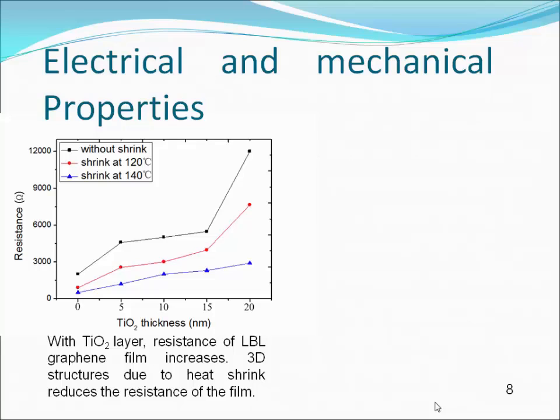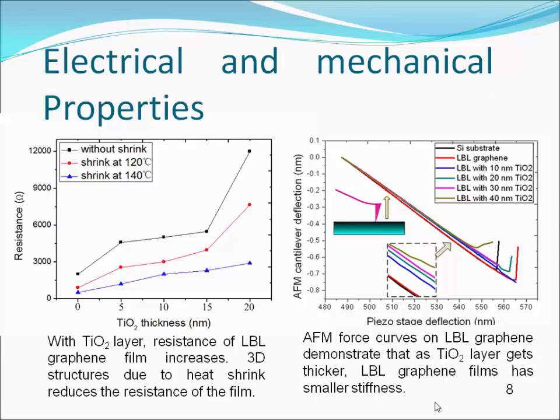On the other hand, the 3D structure after heat shrink can introduce small connections between the graphene nanoplatelets. So as a result, it can increase the conductance. Therefore, the resistance of these graphene components can be changed and tuned by the titanium oxide layer thickness and the heat shrink temperature. We use an atomic force microscope microcantilever to indent the surface of layer-by-layer graphene components to study its